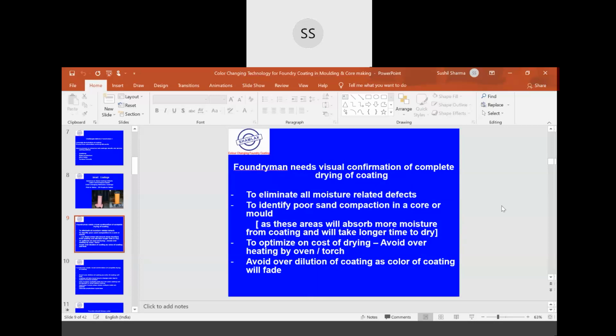So the foundryman needs a visual confirmation of complete drying of the coating to eliminate all moisture related defects. If there is moisture, as you can understand, you can have blowholes or fine pin porosity. It helps to identify poor sand compaction in a core or mold, as it will absorb moisture. It also helps to optimize on cost of drying, avoid overheating by torch, and avoid over dilution of the coating, as the color of the coating will fade.